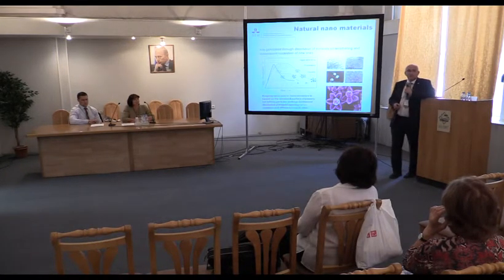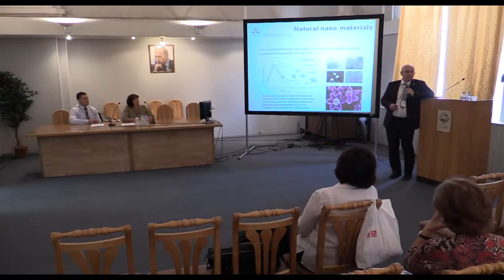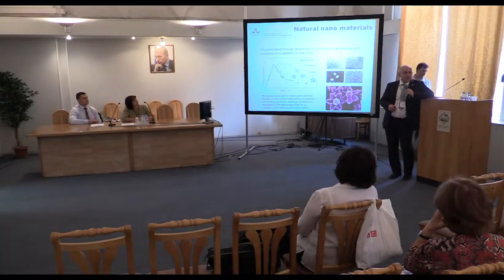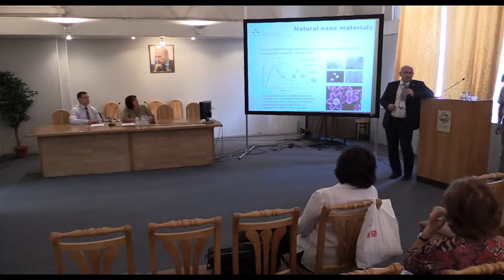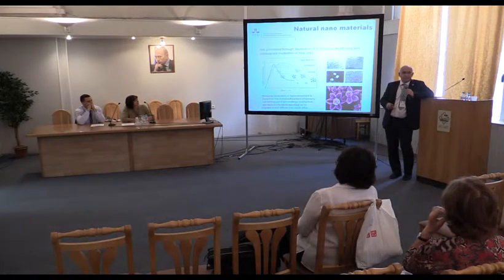So when we're speaking about sol-gel of metal oxides, actually these are sols of metal cations and oxide anions. So the chemistry there, in principle, is the regular solution inorganic chemistry, which is based on nucleation and the processes which follow the nucleation. It can be either growth or aggregation. And if we get particles of nucleation size, 3 to 5 nanometers, what is happening is we're getting a sol which can be very stable, and then when the particles find each other and build a three-dimensional structure, this is a sol-gel transition.